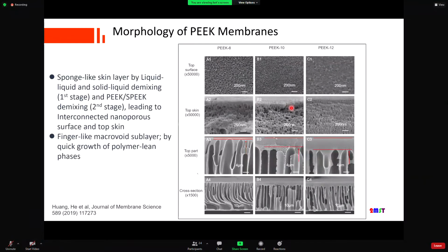If you look at the scanning electron microscope image, the PEEK membrane consists of two parts. First is a sponge-like part, which is really nanoporous with interconnected pores. And the second part is a finger-like macrovoid. Finger-like microvoids are because of fast development of this phase separation process, as I showed you in the previous slide. And the nanoporous structure, we think, is because of the two-stage demixing process, especially for the polyether ether ketone and the sulfonated polyether ether ketone demixing in the second stage.